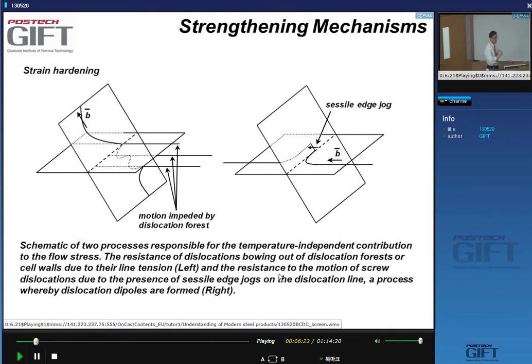All right. But we had arrived at the point of strain hardening, and I had told you that the strain hardening was due to the interaction of dislocations on their glide plane, cutting through a dislocation forest. Now, these pinning points here are obstacles that can be cut through. These are not permanent pinning points. Dislocations can cut through each other, and usually that leaves what we call a jog on the dislocations. And in certain cases, not all cases of intersections, you will form sessile jogs, and they are very strong pinning points.